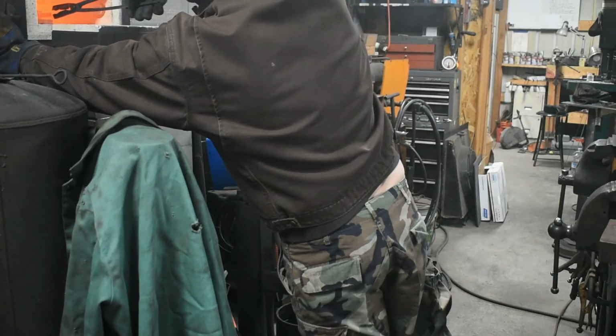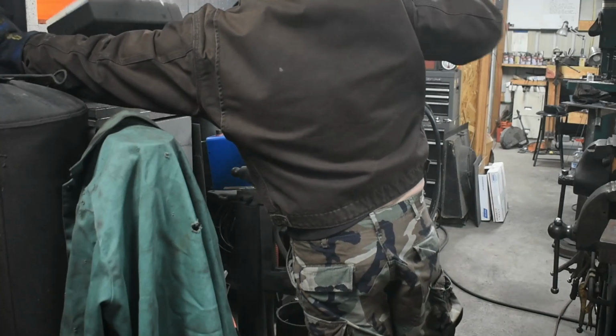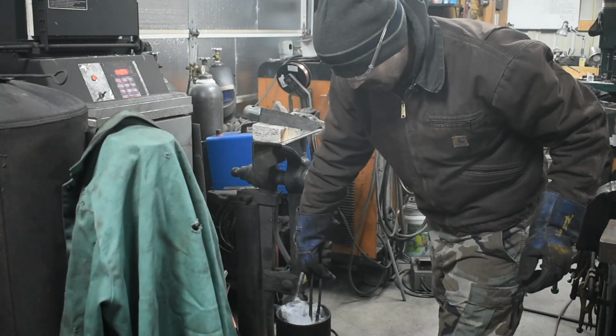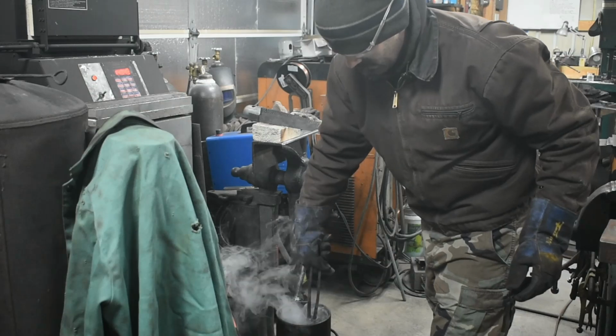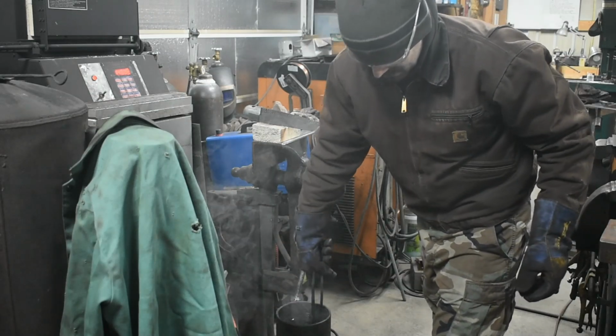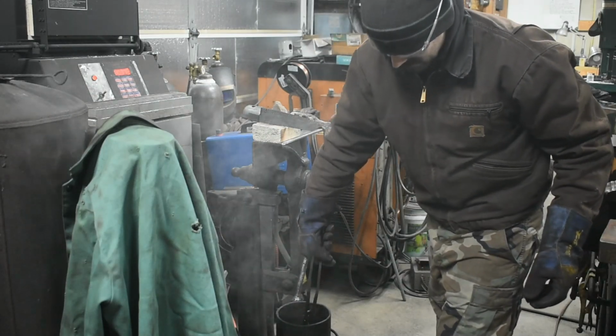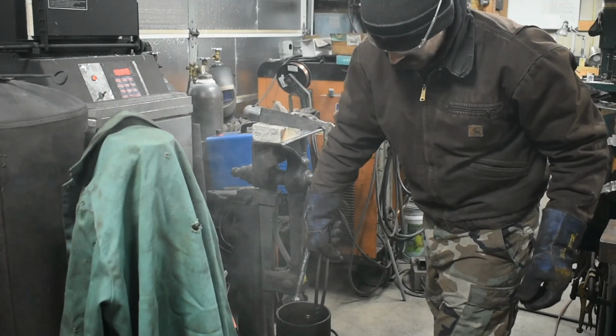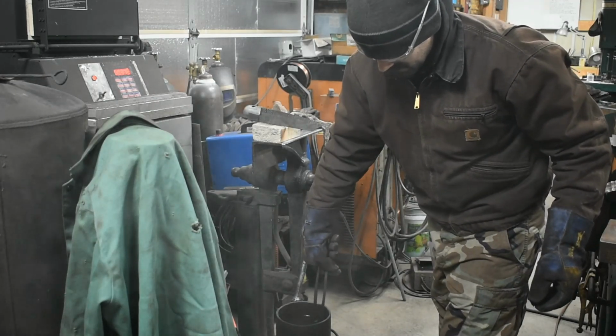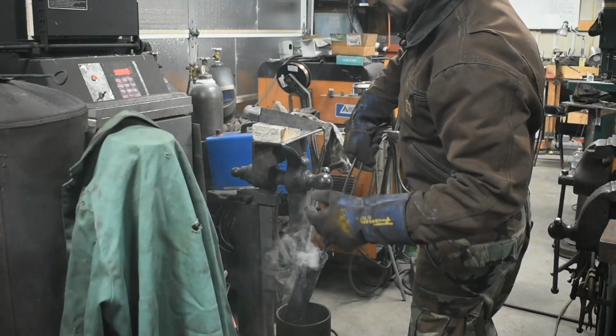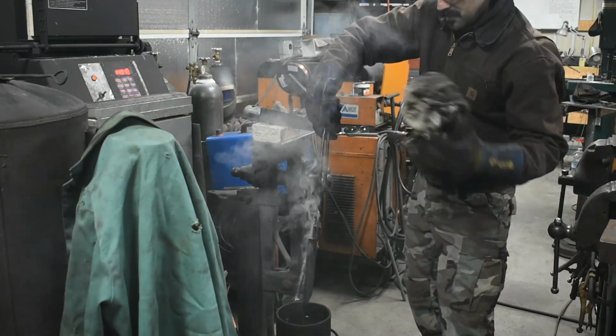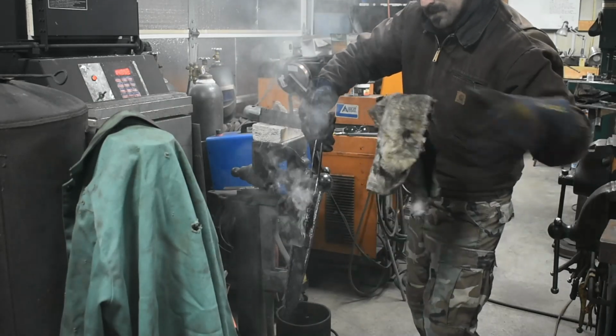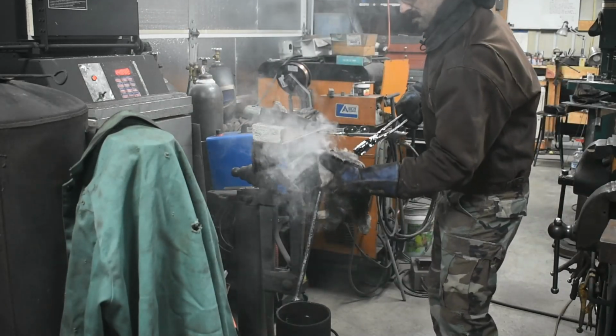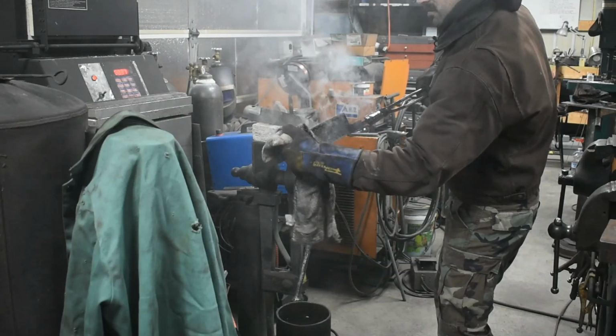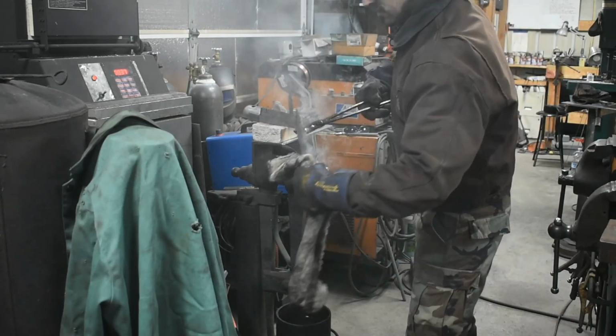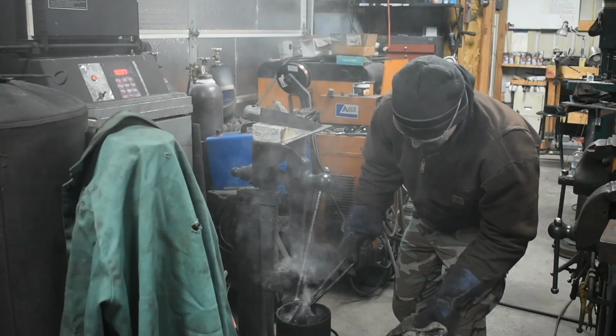Going right into blade number 2. This is the tall bunka. So get that count done, pull it out. Again, mop it up, flip it over, get the bolster a little bit more. That bolster is still a few hundred degrees hotter than the blade, and the heat from that will bleed down toward the heel of your blade if you don't watch out.